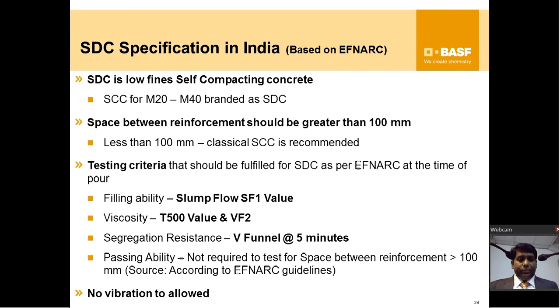So what is SDC, in summary? It is a low fine self compacting concrete for grades M20 to M40. It can be used where the reinforcement space is more than 100 mm. If you have congested reinforcements, you use a classical SCC, which means a high amount of fines, and instead of 20 mm aggregate, go for 10 mm. Those sorts of changes need to be done. But for spaces greater than 100 mm, you can fully use it. Especially for mass pours and modular formwork, SDC can do the job much better.